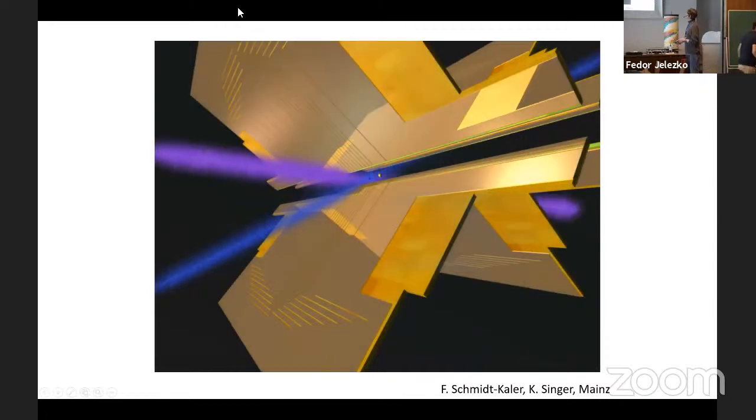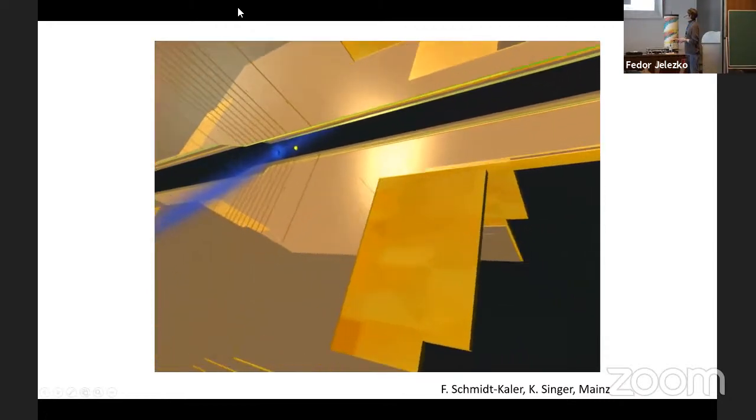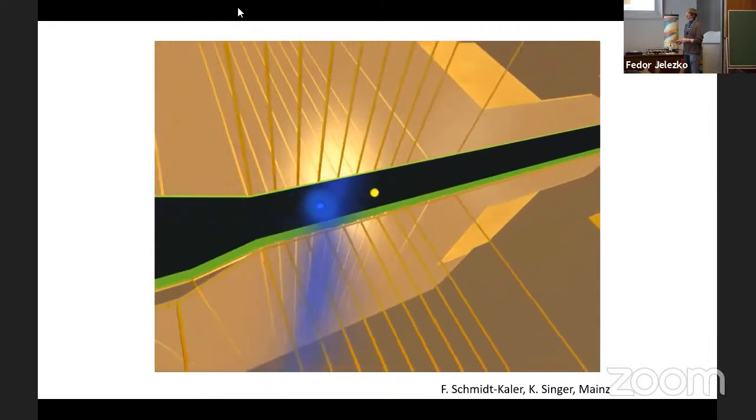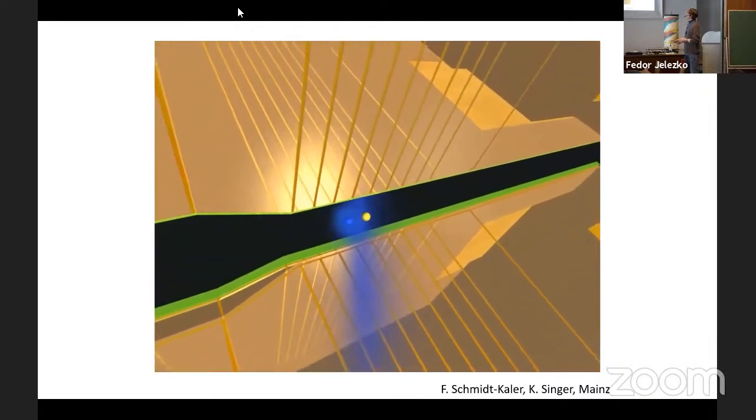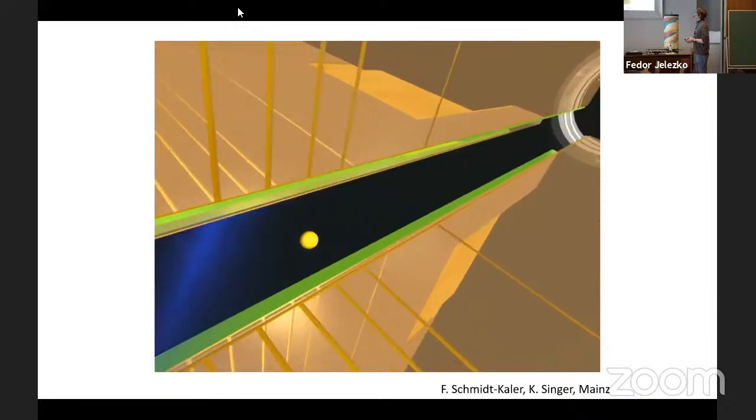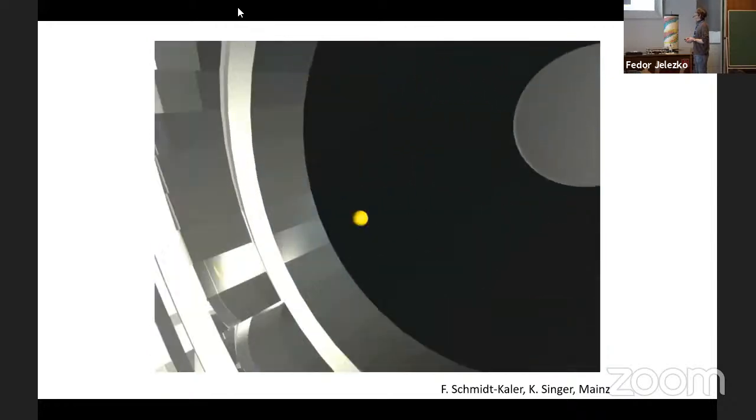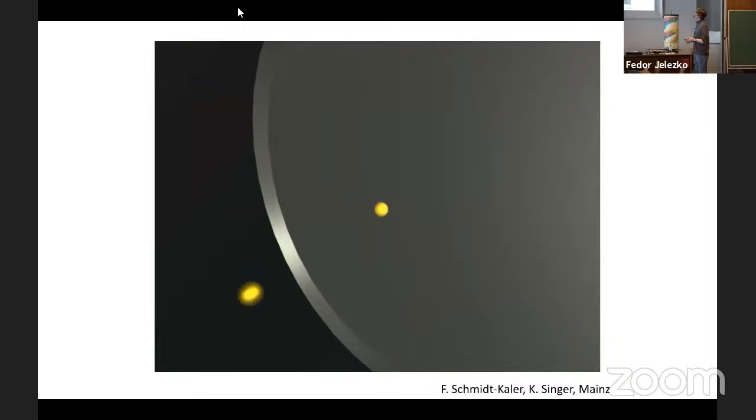So the ions get first trapped, and you see two of them. One can be cooled, and the other is a nitrogen ion, which is not cooled directly, but cooled sympathetically because it has a certain coupling via vibrational modes. Calcium is released, and nitrogen is now accelerated and placed into diamond one by one. That's a very precise method in terms of the straggling, because the trajectory of the ion can be very well controlled. It's a very cold ion. There is no thermal motion.